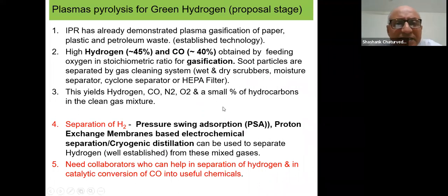Recently, you might remember the Prime Minister gave a call for production of green hydrogen using different technologies. Now, we've already demonstrated the process of plasma gasification of paper, plastic, and petroleum waste. This is established. These things end up giving you a high percent of hydrogen, 45% hydrogen, 40% carbon monoxide, depending on the amount of oxygen you feed and so on. You would, of course, need some soot particle filters, HEPA filters, and so on. So you end up with different percentages of hydrogen, carbon monoxide, and so on. Using some techniques like PSA or proton exchange membranes, you would need to separate out the hydrogen.